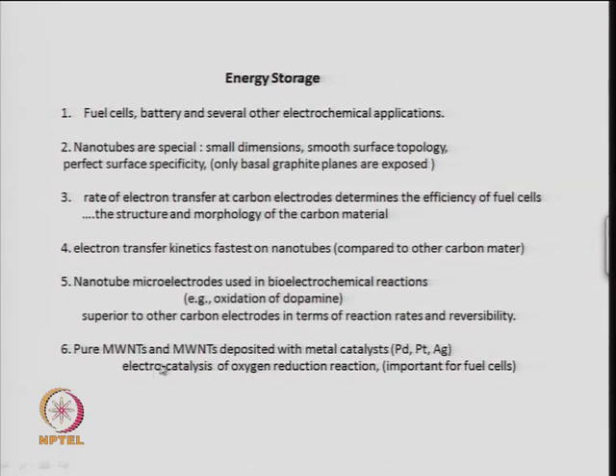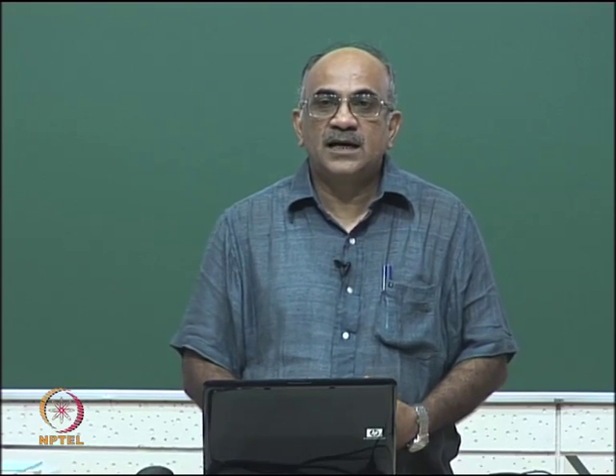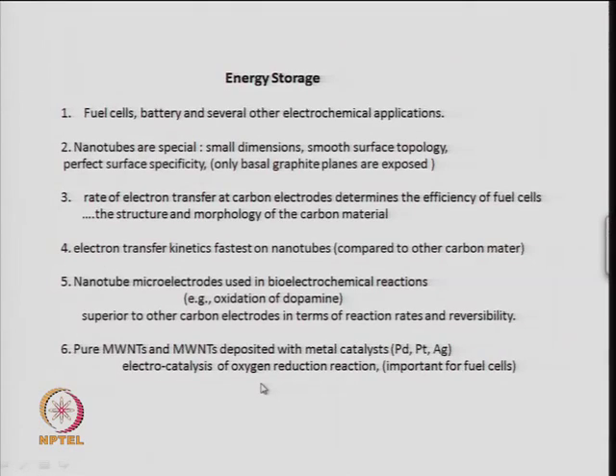Pure multi-wall nanotubes and metal catalyst-deposited nanotubes are very important for heterogeneous catalysis. Metal-deposited carbon nanotubes have been used for the oxygen reduction reaction — critical for fuel cells where oxygen is reduced at one electrode and hydrogen enters from the other to generate energy and water. Multi-wall nanotubes doped with metal catalysts show very high efficiency for this oxygen reduction reaction.